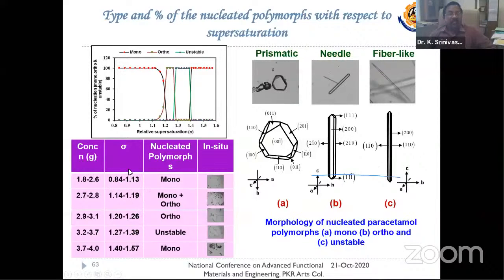So we were able, for the first time, to segregate the regions of nucleation of different polymorphs of paracetamol. See, within this supersaturation region, I'm speaking of the relative supersaturation, we could achieve only the mono nucleation of the paracetamol. In between, there are mixed regions where both nucleations appear, whereas in another region, only the ortho nucleation. So when you set the conditions for this particular region, you can crystallize only the desired polymorph. So this is an outcome of the process.